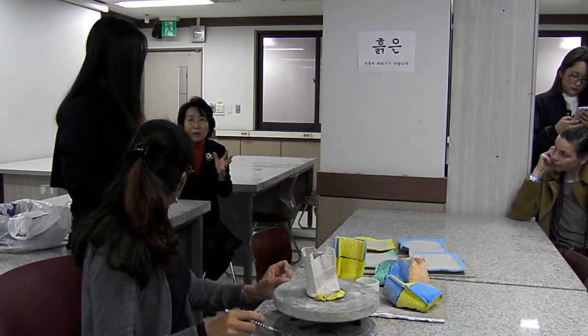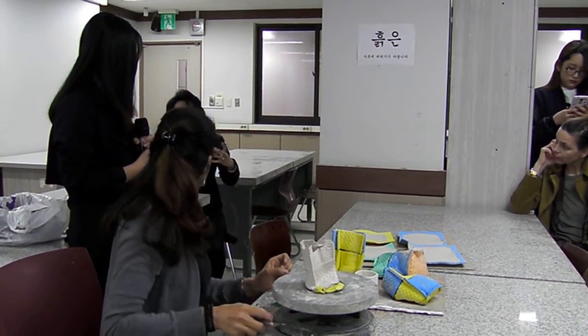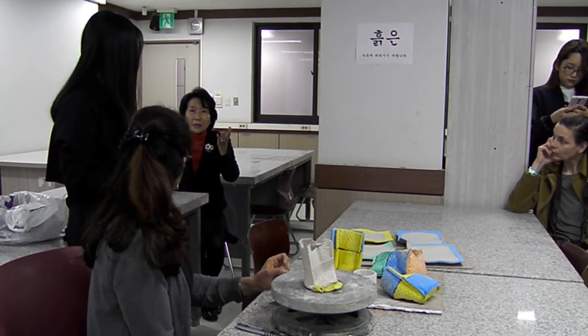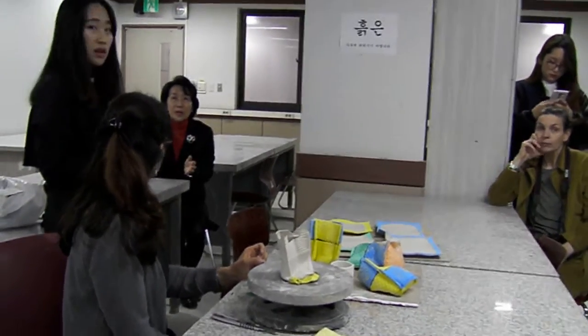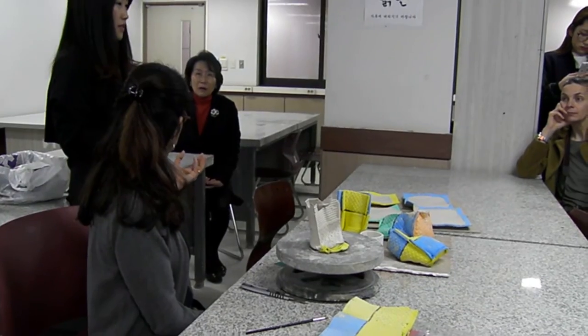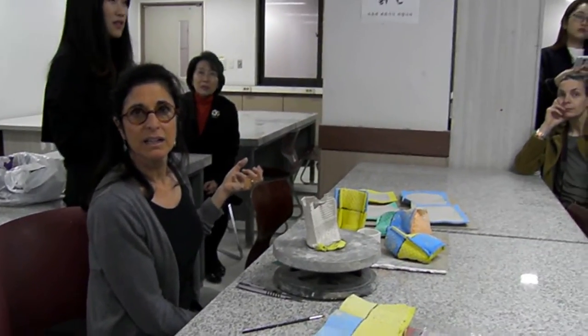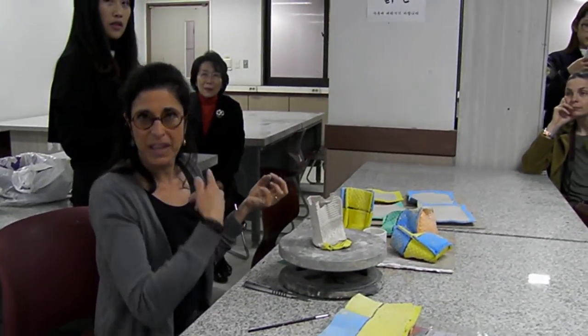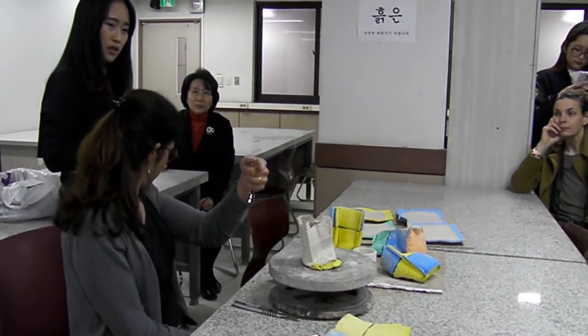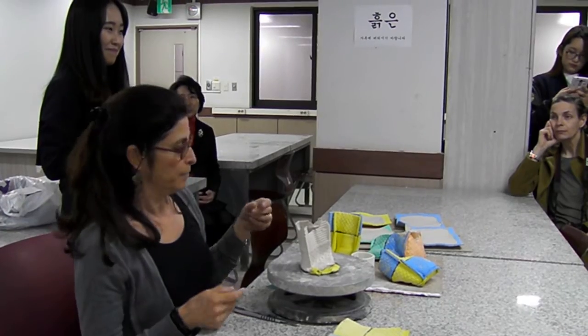So for making an even liquid, the grain of clay has to stay up, to keep it suspended. But don't they put a deflocculant in it? Yes, you put a deflocculant in it. Sodium silicate is what we normally use. That's a deflocculant, but I don't think she's talking about silica. In this slip, was there one? Yes, already.